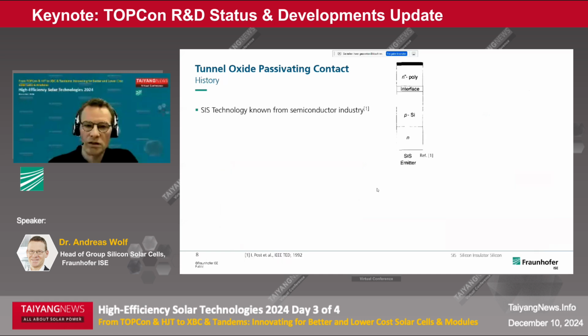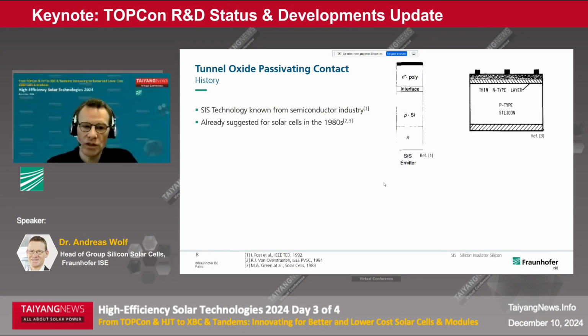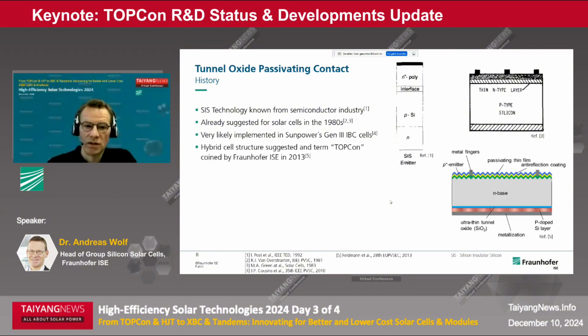Now, this technology has been around for quite a while. It was known in the semiconductor industry as silicon insulator silicon. It was suggested to be used in solar cells quite early in the 1980s by Martin Green, among others. And it was very likely implemented in SunPower's Generation 3 back contact solar cells. And then in 2013, Frank Feldmann from Fraunhofer ISE introduced this hybrid cell structure with a TOPCon full area contact on the rear side and a boron diffused front junction. And in this publication, we also coined the term TOPCon.